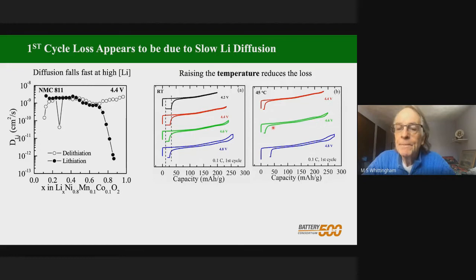The green one is similar, and the blue one is again similar, but you see now this gap here is increasing because we've got these damaging side reactions. So we now know our electrolyte is really only stable up to about 4.4 volts, but if we're patient, we can get the lithium back in.